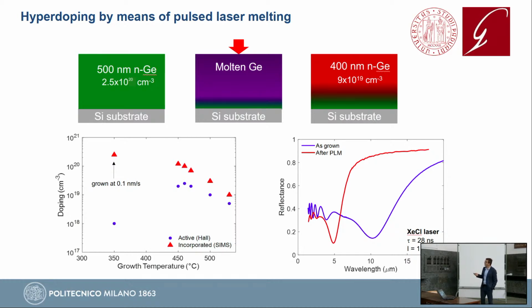So again, we relied on pulsed laser melting. So here you see a set of samples where we have, again, Hall effect and SIMS, this time as a function of temperature. So again, if we go down in temperature, we see that we can incorporate much more phosphorus, so we can go up to 10^20. But again, we see that actually the conductivity is very poor. Only, let's say, 1 out of 1,000 of these atoms is actually activated. But again, if we shock our system and let it melt and then recrystallize in a few nanoseconds, the phosphorus will get in the right place, and we can actually have a jump in the plasma frequency and cover all this range.